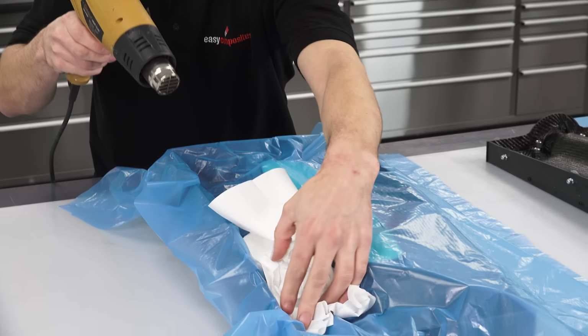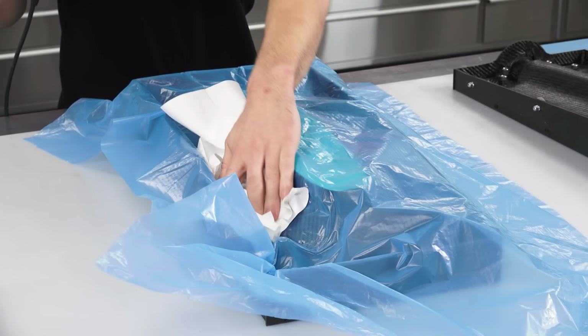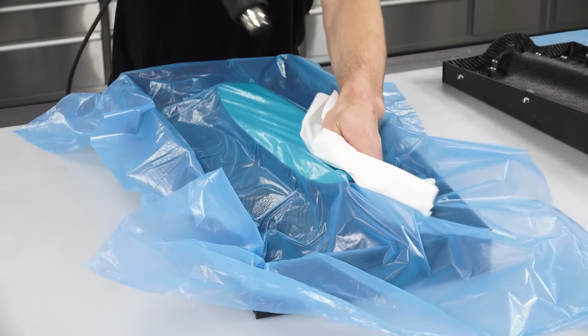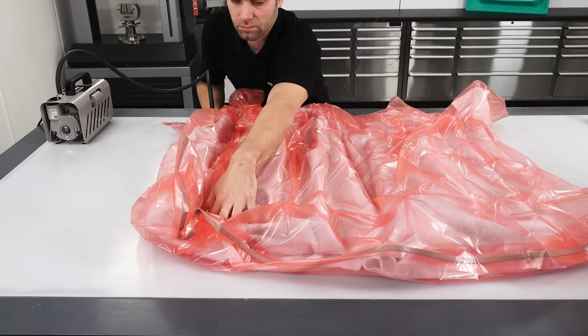After laminating the full ply, they are debulked. This involves putting a layer of perforated release film, followed by breather, and then consolidating under full vacuum for 20 minutes to ensure good consolidation against the mould.